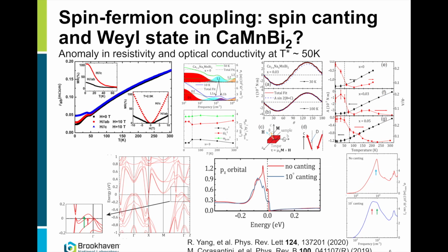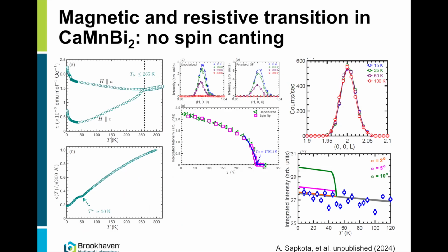But we can detect 10 degrees in a neutron scattering measurement, because the appearance of a homogeneous magnetic moment on top of the lattice would mean that the lattice Bragg peak would have to increase at the temperature where the ferromagnetic moment arises. And so the calculated increase for this weak lattice Bragg peak that we have measured, for 10 degrees, would be like that, and that's nothing that we see. So there is no canting. This here is an order parameter that we measure. The magnetic order appears at around 270 Kelvin, and there is nothing in the order parameter corresponding to this anomaly at 50 Kelvin. The susceptibility is basically consistent with the order parameter showing the antiferromagnetism.